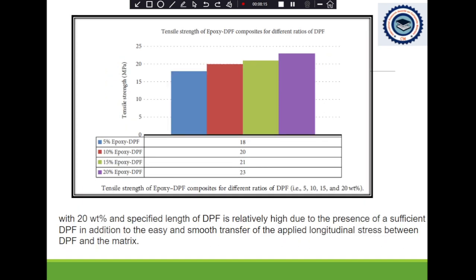About the last mechanical test, the tensile strength of the epoxy date palm fiber composite for different ratios of date palm fiber: 5, 10 weight percent, 15, and we can see here the maximum tensile strength was for the 20 weight percent of fiber. This is because there is sufficient date palm fiber, in addition to easy and smooth transfer of applied longitudinal stress between the date palm fiber and the matrix.